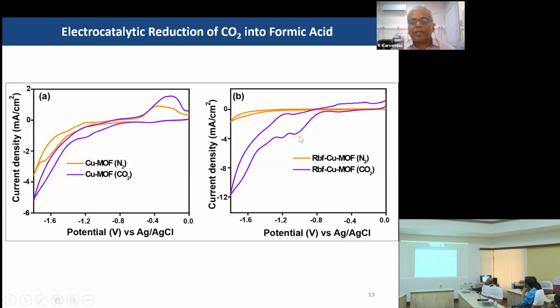If you look at the cyclic voltammograms, when this riboflavin modified MOF was used as a catalyst in the presence of carbon dioxide saturated electrolyte, you can see the current density is greater, very close to -12 milliampere per centimeter square. This clearly indicates that the riboflavin modified copper MOF is a superior catalyst for the reduction of carbon dioxide compared to the pristine copper MOF.